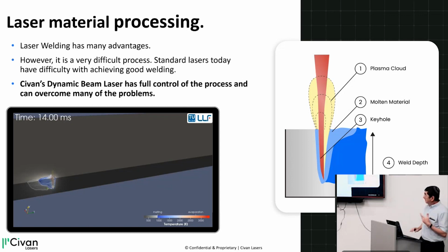Laser, because the energy is so focused, within a few tens or hundreds of microns, you can get kilowatts or tens of kilowatts. The heat just doesn't have time to spread to the sides because of the heat conductance of the material. It just happens so fast that you get to the melting point and even to the boiling point, and you get evaporation of the material. So what happens is that in the point where the laser penetrates the material, it melts the material, evaporates it, and because it evaporates it, it can penetrate even deeper.